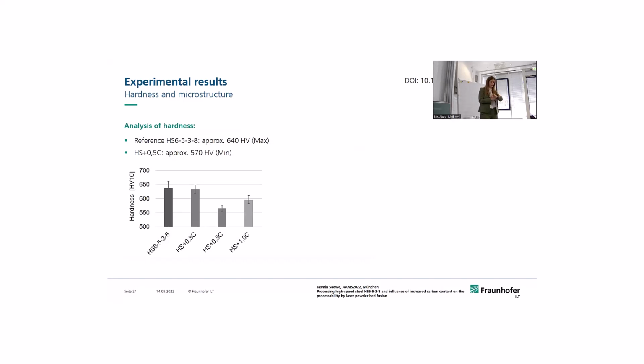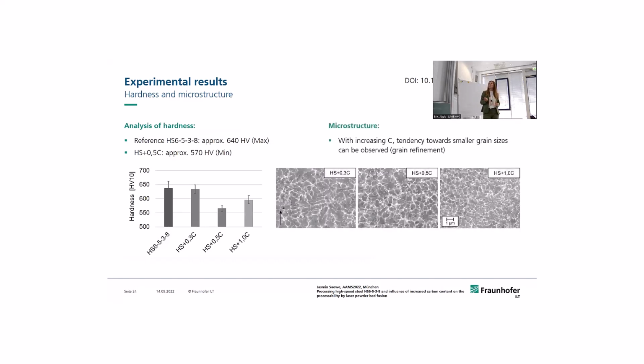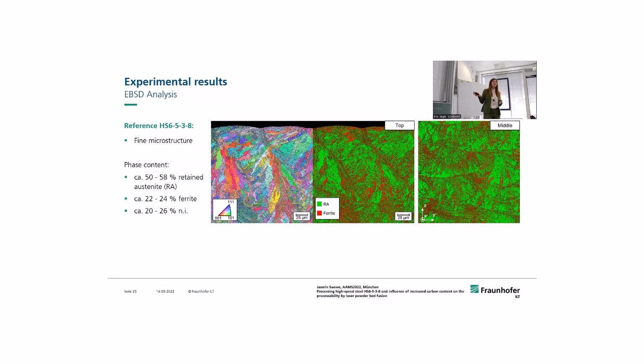I will talk about it in a minute because I have to hurry up a little bit. We see that in the microstructure, we have a grain refinement by adding 0.3 to 1.0% carbon content, and a lot of carbides. I don't show the XRD analysis here, but we know they are carbides. This is the reference, the standard HS6-5-3-8. We see a lot of retained austenite already, about 50 to 60%.